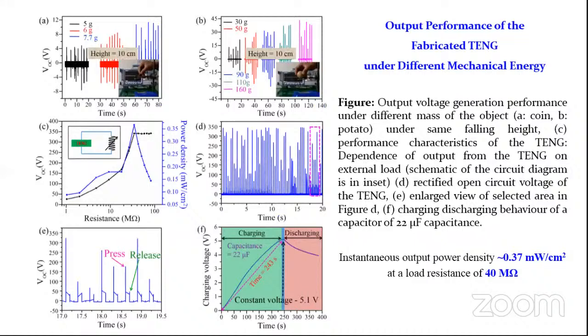Our fabricated device is also able to harvest energy from several kinds of mechanical motions. When a coin falls from a height of 10 centimeter, it produces around 9 volt of open circuit voltage. Then we have also checked the output performance under potato falling, with potatoes of several weights. With increasing weight of the potatoes, we have seen that the output voltage of the TENG increases. And there are several experiments, as I said before. I can say that one capacitor with a capacitance of 22 microfarad can be charged up to 5.1 volt in just around 250 seconds. So we can easily harvest energy from mechanical motions, as well as store it in the capacitor in a very short time span.